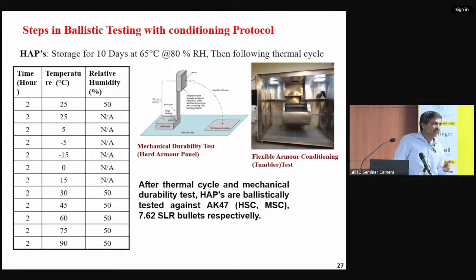So the testing protocol of the bulletproof jacket is very stringent, and this is the reason why the selection of the materials, especially the ceramic, plays a very important role. If in the drop test we find cracks, those cracks will attract the bullet, because the aiming of the bullet will be intentionally at those cracks. So the important thing is that while we are processing the ceramic, the fracture toughness should be high, so that at least in the drop test we should not have cracks.